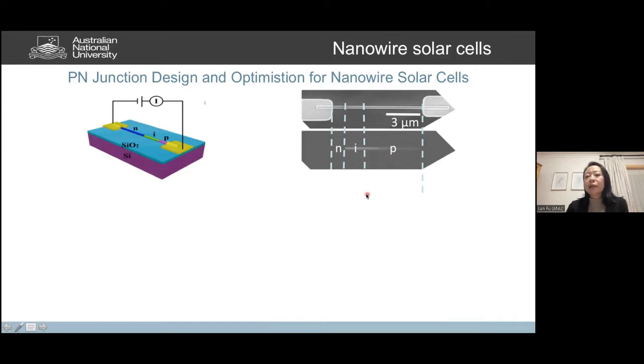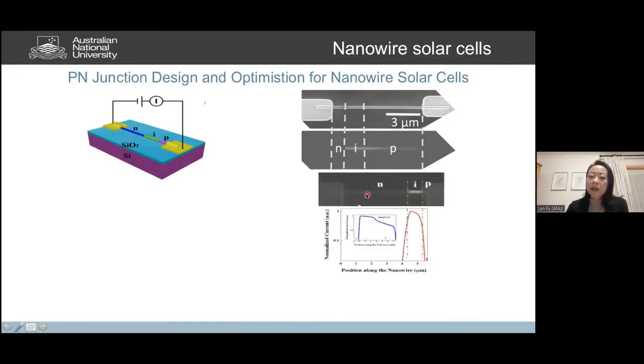So using this technique, we can really understand the device structure. If we change the growth sequence by growing NIP to PIN, you can see that the built-in electric field profile actually changed due to the different growth sequence. That's related to different growth rates during nanowire growth, as well as different doping distribution in the nanowire.